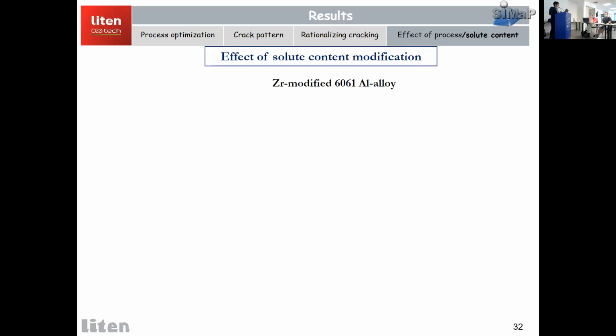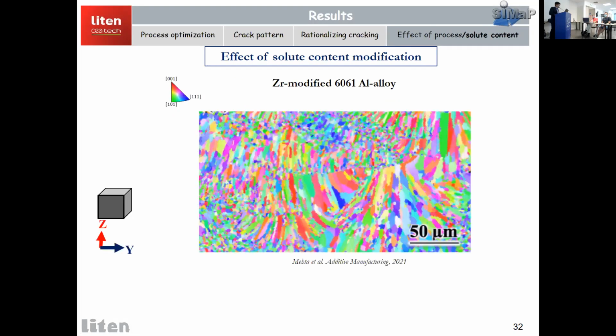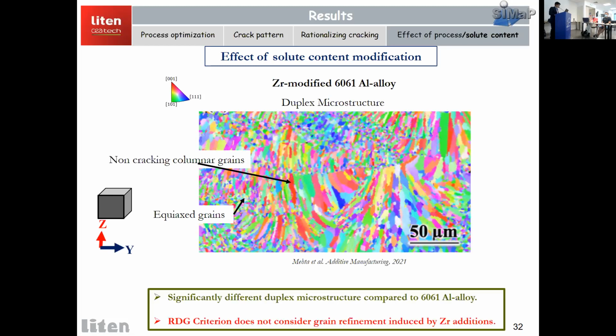So to identify what is lacking in the model, we thought, okay, let's check the microstructure of the zirconium modified 6061 aluminum alloy. The microstructure is quite complex here. Compared to our standard 6061 aluminum alloy, we clearly see a duplex microstructure, with columnar grains, the long elongated grains here, and equiaxed grains present simultaneously. So it is quite different. This is probably the reason the RDG model was not able to consider the grain refinement introduced by the zirconium, and why we were not able to capture the beneficial effect of zirconium in the 6061 aluminum alloy.